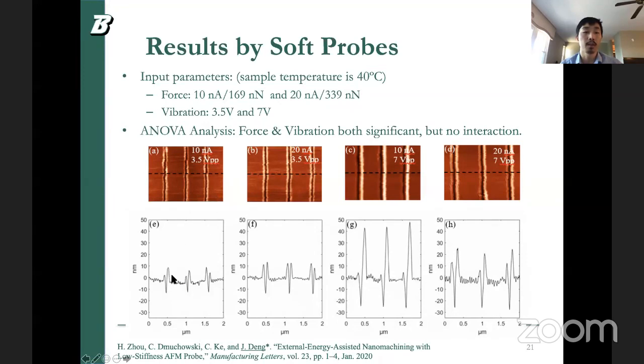We can fabricate very clear trenches, not only indentations, with about 10 nanometers using the small temperature, small vibration amplitude, and a little bit larger depths. This result can be found in the paper published in Manufacturing Letters.